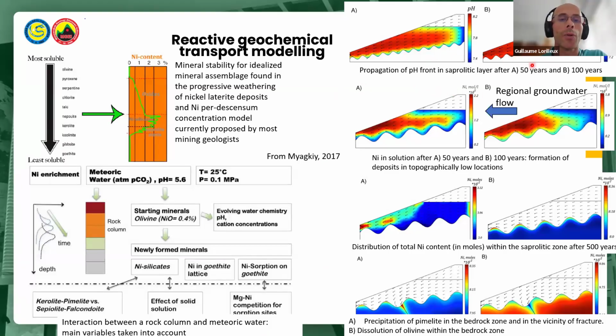And the top diagram shows the propagation of the pH front. So with time, we can see the pH front moving downwards. And nickel in solution also increasing downslope with time. And also the nickel content increasing in the saprolite in the topographically low areas with time, as well as the upper part of the bedrock here. And the last one here represents the actual dissolution of olivine.